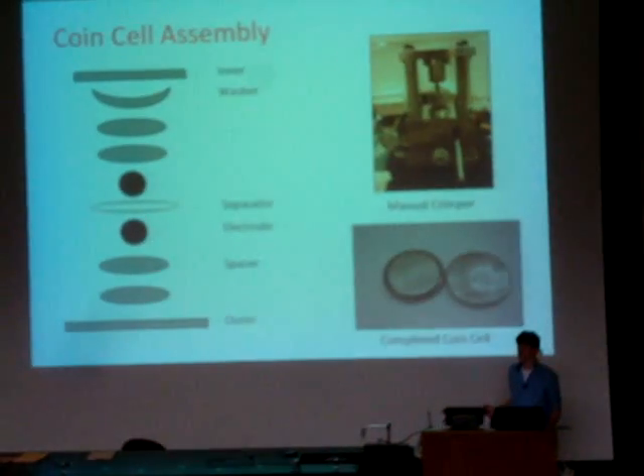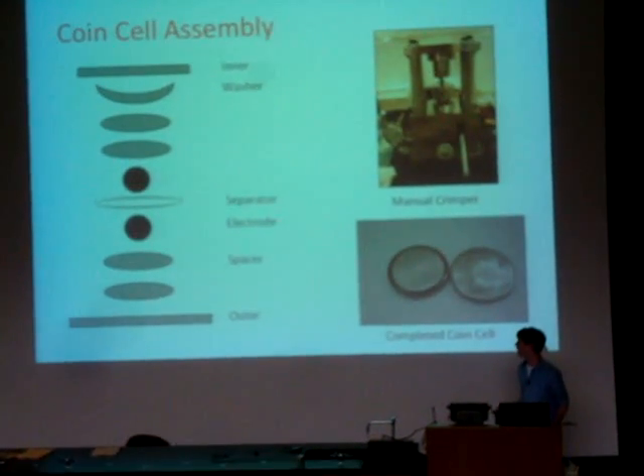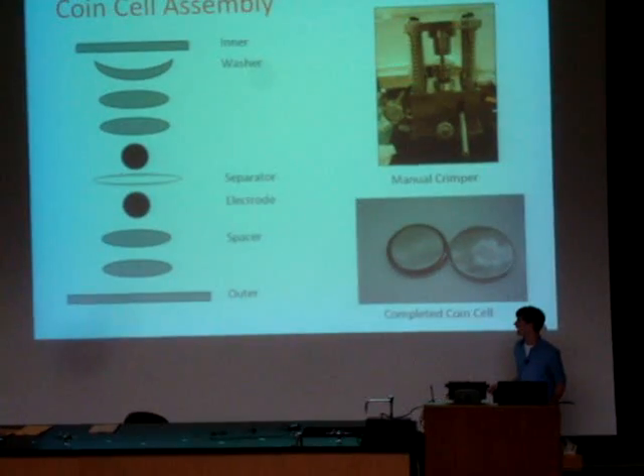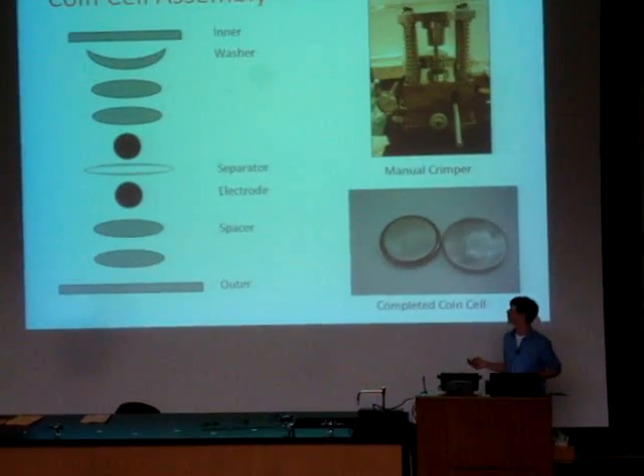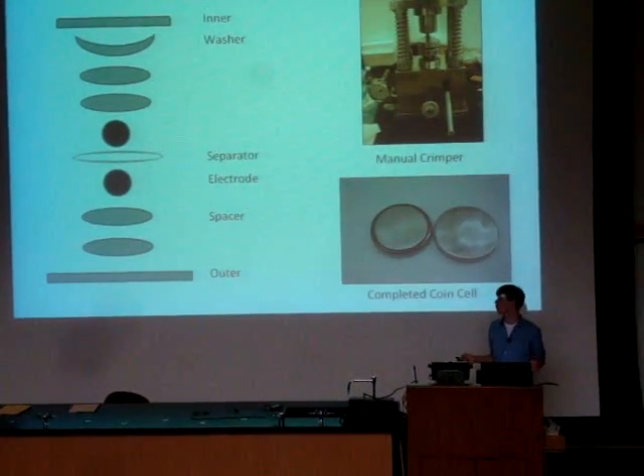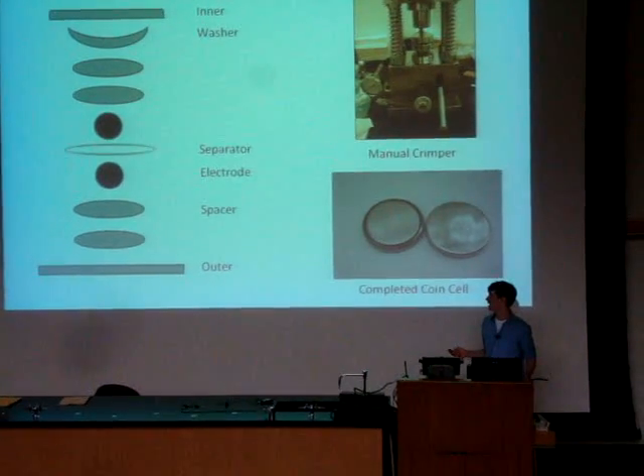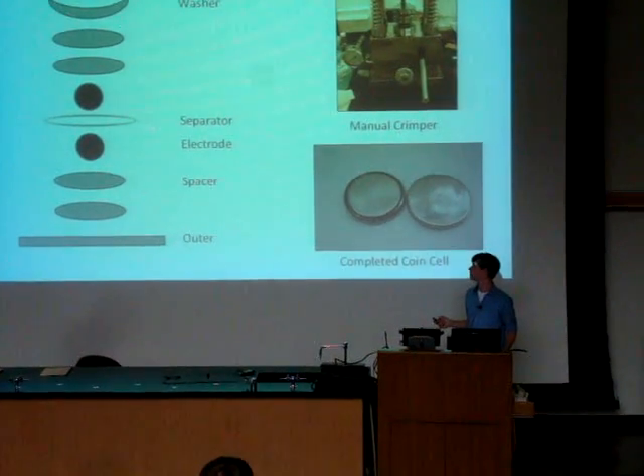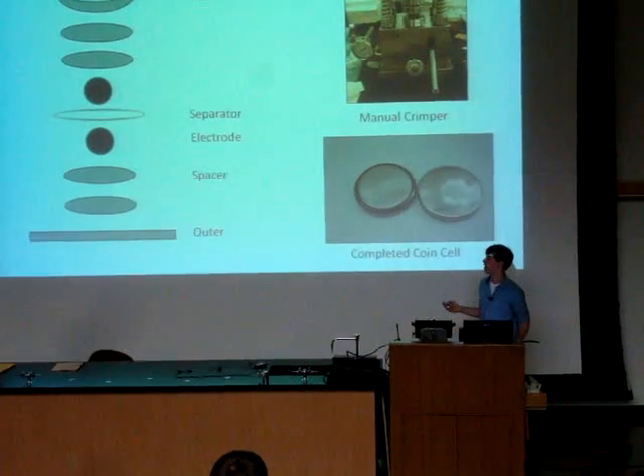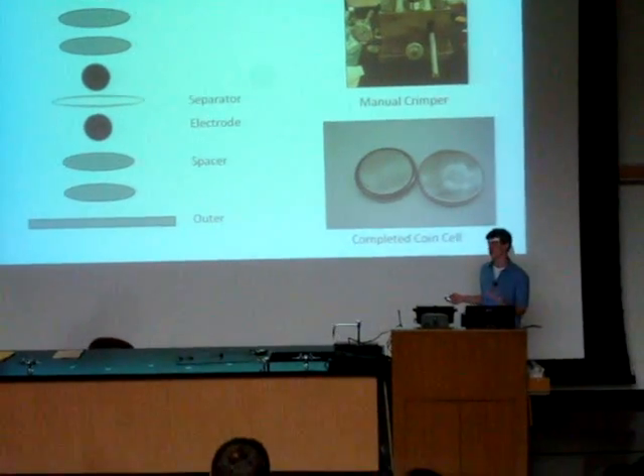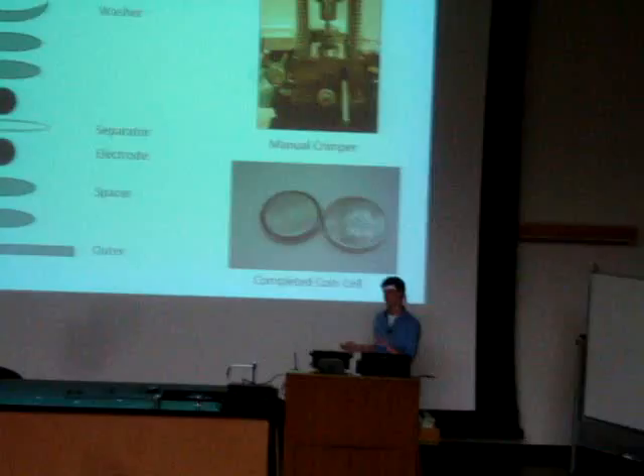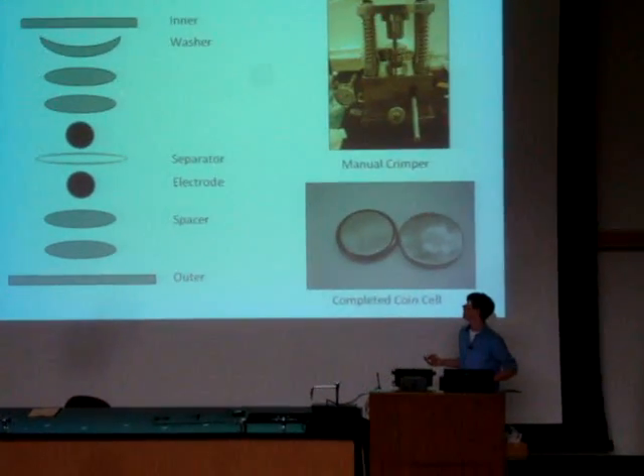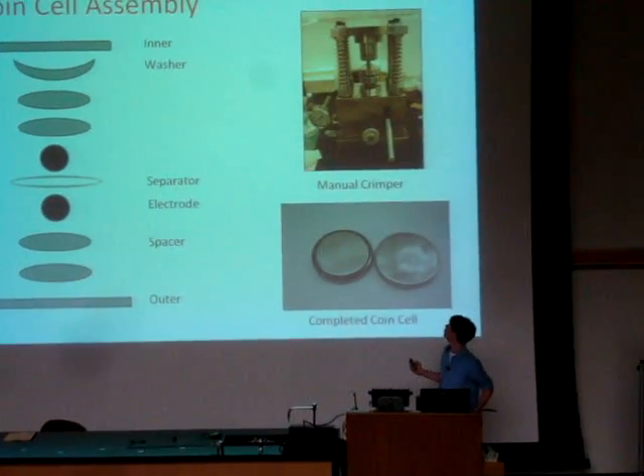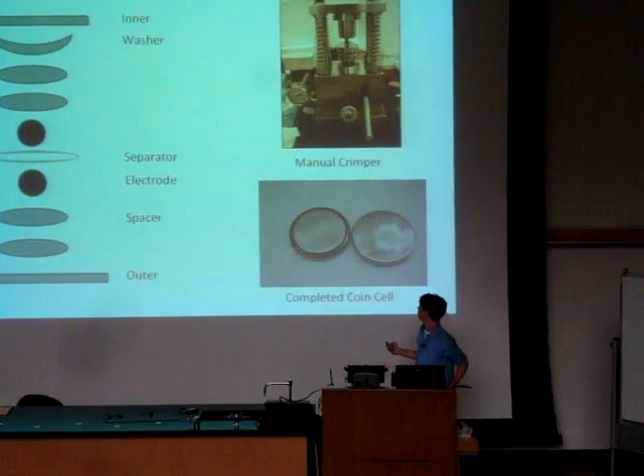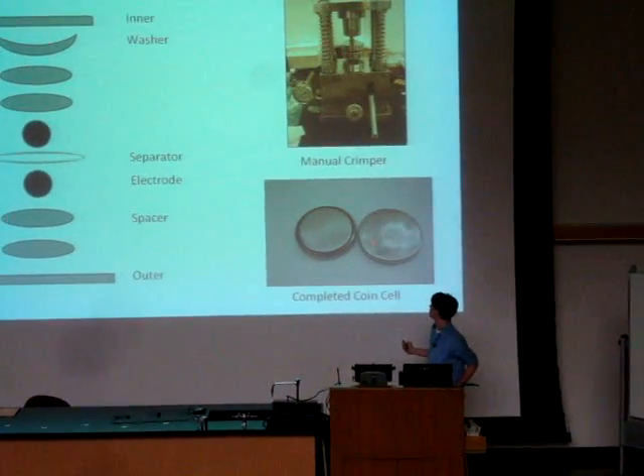This is simply coin cell assembly. We worked with a stainless steel outer, added 2 spacers, an electrode. Then the electrolyte solution of 1 molar TEABF4 was added. Then a spacer was added to make sure the circuit doesn't short. Second electrode, 2 washers, and then 2 spacers and a washer to make sure that the electrodes are held in place and constant contact is added. And then an inner was added to cap it. Then it was put in a manual crimper, and then it was sealed, and this over here is a completed product of a coin cell.